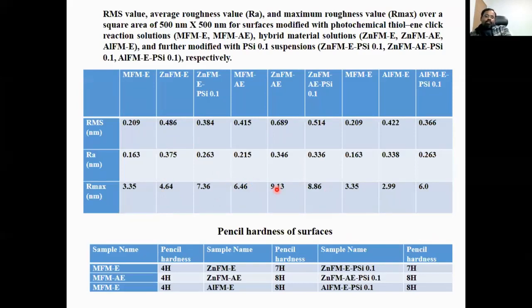Also we check the hardness of the coated substrate using the pencil hardness test. So it shows that our coating material without loading metal is good hydrophobic, and the hardness is around 4H. It's quite good for some applications, because 4H is enough for different applications. But while modifying this thiol-ene click reaction solution with metal source, zinc and aluminum, the hardness is highly improved. And after the second layer coating with the silica also, the hardness is maintained and also shows very good robust surface property on the coated substrate.